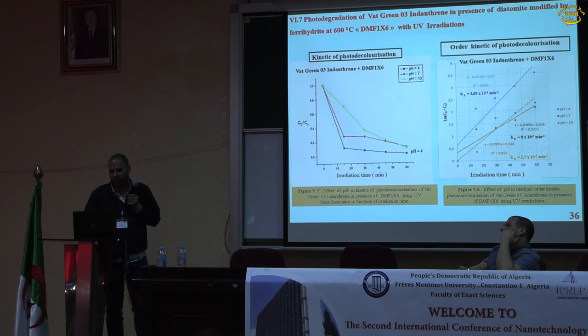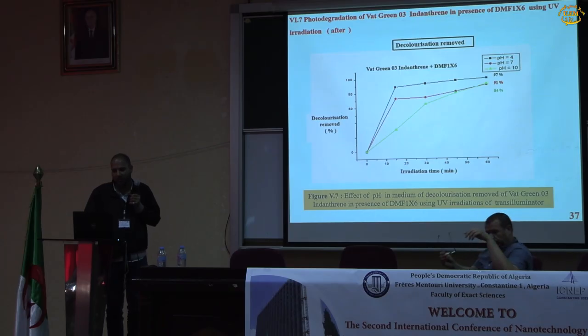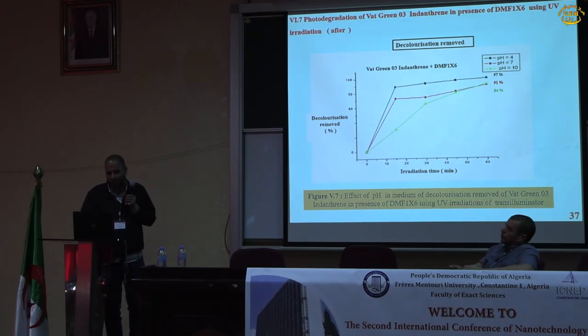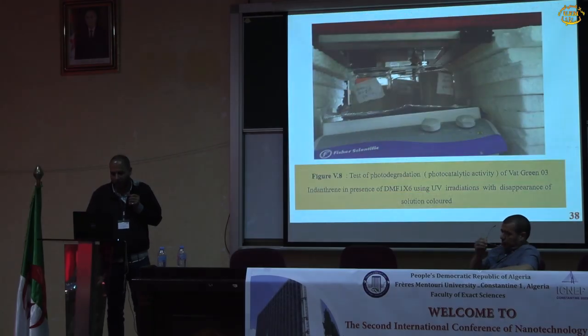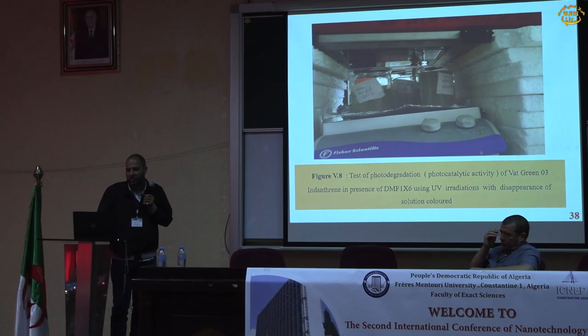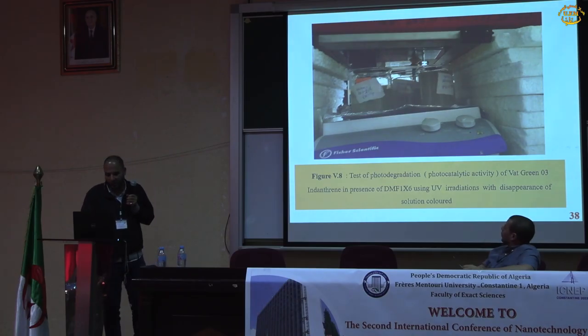The kinetics of photodegradation follow first order, and the best result is at pH equal 4, with decoloration removal of 97%.